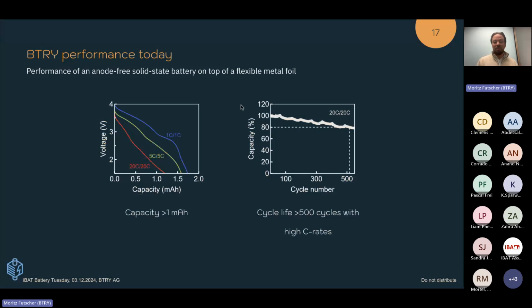And here you can see how such a cell performs today. Here you can see the capacity of our cells. So we are already in a regime of above 1 milliampere hour, which might not seem a lot to people coming from bulk batteries. Coming from thin film batteries, this is a huge step forward going in this direction, because typically we are speaking of a few microamp hours. So we already have milliampere hours, and we can show that we can also cycle them for a very long time and at fast C rates.